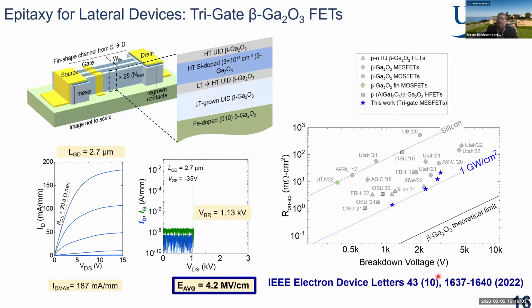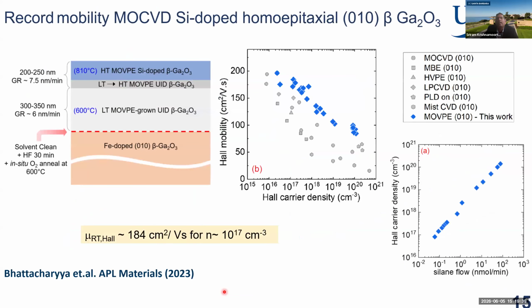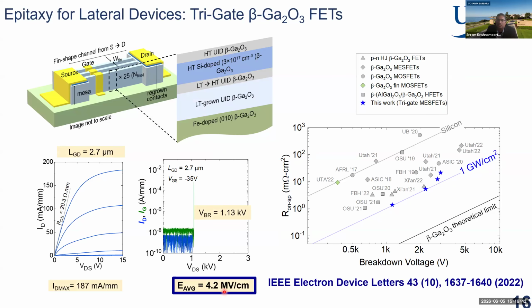And these channels are also capable of handling high electric fields. So for instance, with just 2.7 microns of gate-drain distance, we're able to block 1 kilovolt. So that translates to an average electric field of about 4.2 megavolt per centimeter, which is higher than the theoretical electric field handling capability of gallium nitride and silicon carbide. So basically, the large growth window helps us get high mobility, and we can then translate that to high electric field handling capability in these devices.